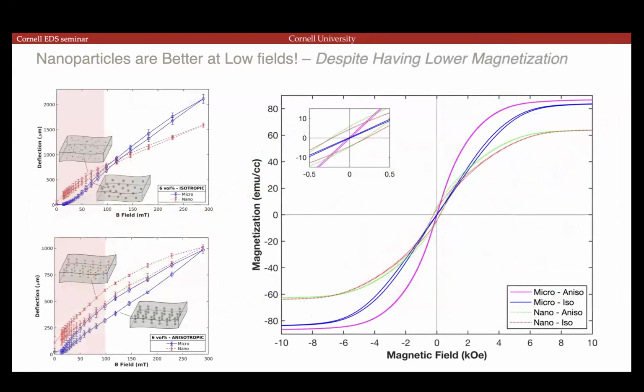So if you look back at the magnetization curves, overall, what you see is that if you apply a large enough field, the effect that I said is true. The nanoparticles, because of the loss of magnetization at the edges and the surface to volume ratio, do have a net lower magnetization than the microparticles, but the true reason for their better performance is this tiny little section here. If you spread it out, the nanoparticles have what we call higher remnant magnetization, or higher magnetic moment when there's no field applied.